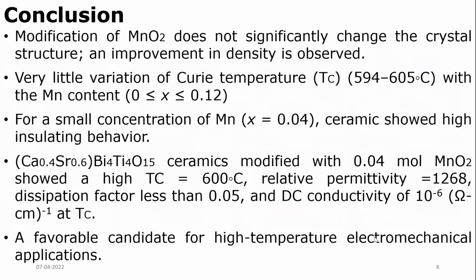So we can conclude that modification with MnO2 does not significantly change the crystal structure. However, an improvement in density has been observed. Little variation of Curie temperature is seen with the increase of the Mn content. For a small concentration of Mn, the ceramic shows insulating behavior. Out of all the doping, with the doping of Mn 0.04, it shows high TC, relative permittivity, a dissipation factor which is less than 0.05%, and better DC conductivity.